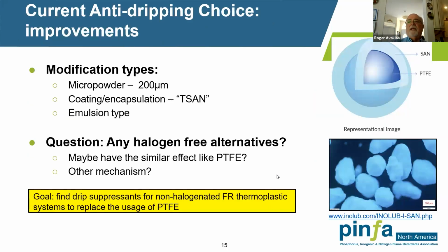Indeed, encapsulation with a styrene acrylonitrile shell, so-called T-SAN, has really alleviated a lot of these issues with regard to agglomeration or the change in the crystal morphology. And indeed, these have been available for probably 30 years or so. Unfortunately, this does not address the two issues indicated in the previous slide: it is still a fluorine-containing system, and you typically do use PFAS-type materials to make the PTFE.